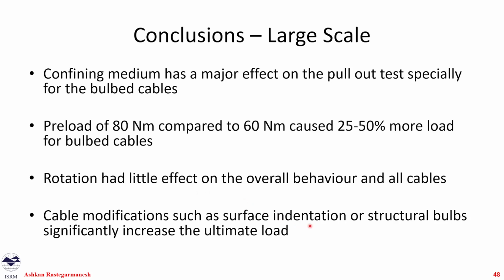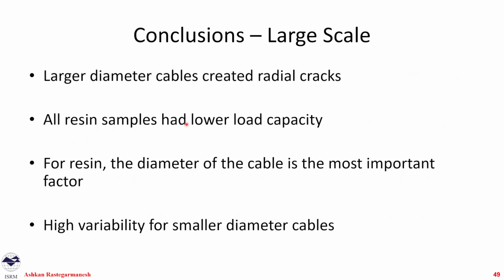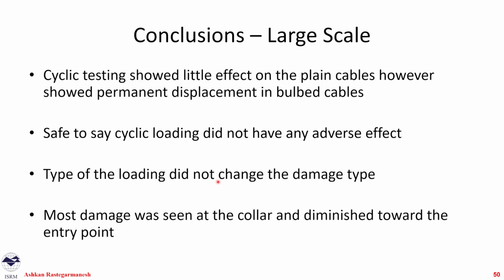Cable modifications such as surface indentation and structural bulbs significantly changed the behavior of the test. Larger diameter cables create radial cracks, if you remember the picture. Our resin samples that we used had lower loads. And for resins, we realized that the diameter of the cable is very important. And we are not getting, in general, good variability for smaller diameter cables compared to the larger ones, regardless of which test we are doing. Cyclic testing had little to no effect. So it's safe to say that it has almost no adverse effect on the behavior.